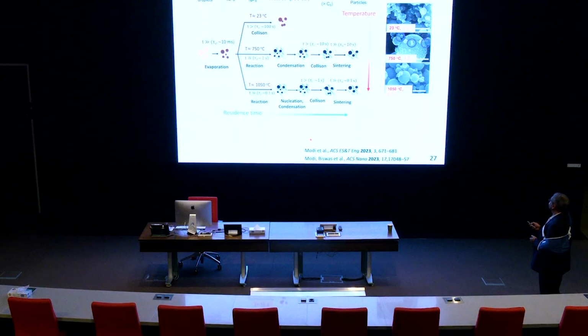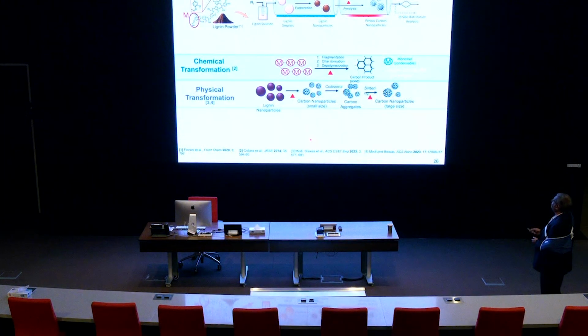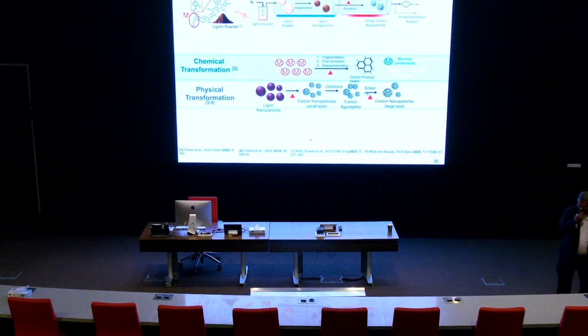So my question, I can start with the question already, is dealing with the lignin. When we now see slide 26, in the very left, the very first step looks very simple. You have lignin powder and then lignin solution and so on. But as far as I know, the lignin is a highly cross-linked material, high molecular weight. And in order to get it in solution, you have to process it. And what you have in the end is lower molecular weight, is non-cross-linked, and it contains sulfonate groups. And this would be my question. Where is the sulfur then? In the end, in the porous carbon nanoparticles, do you still have the sulfonate ions or whatever?